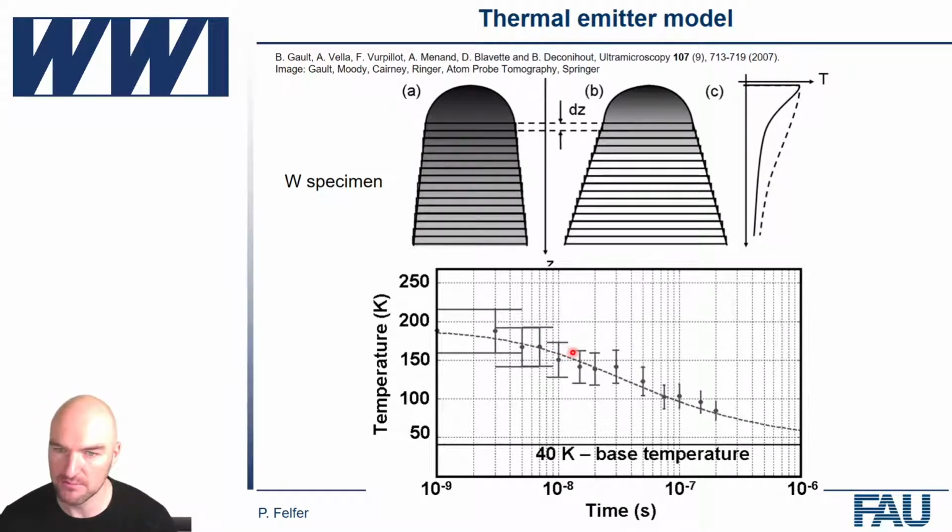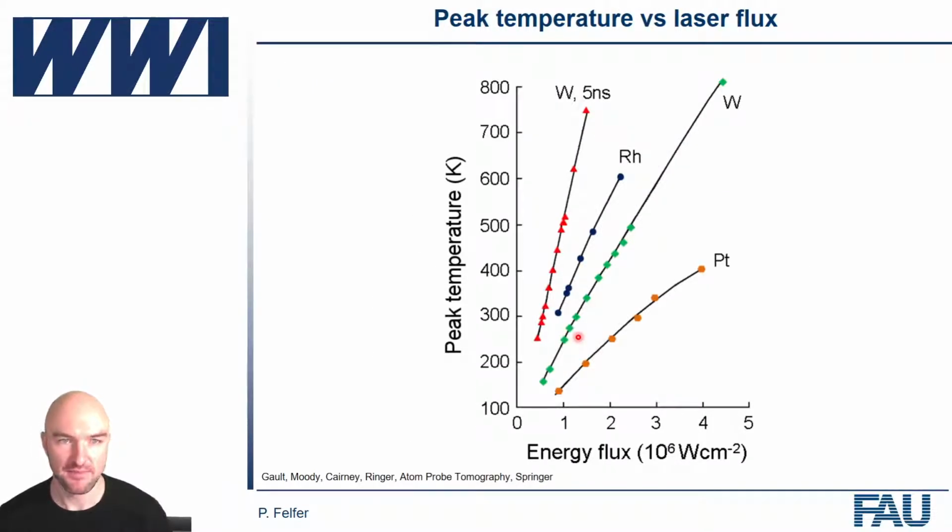The thermal movement, the thermal energy you give to the ion plays no appreciable role. What is important is that all of the ions essentially have, within the accuracy of the power supply, which is going to have some ripple to it, the same energy. Except for the whole ion dissociation thing. So this also plays a role with the energy, but let's assume single atom ions, then they're all going to have the same energy.